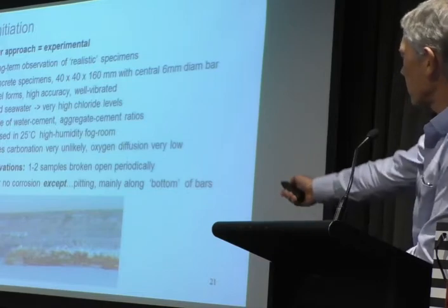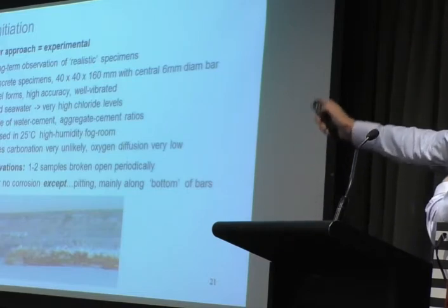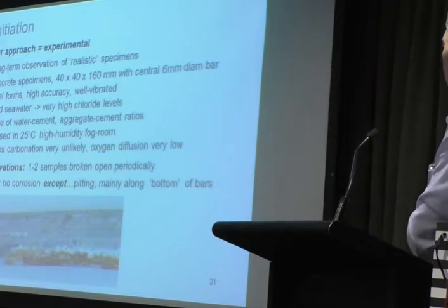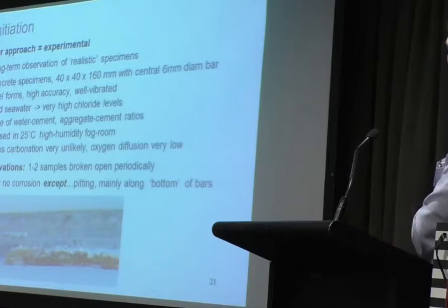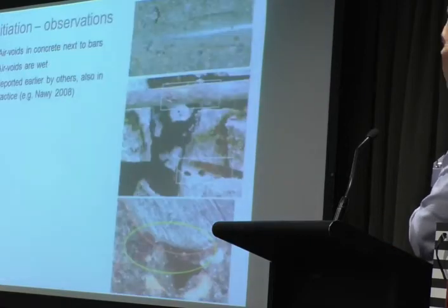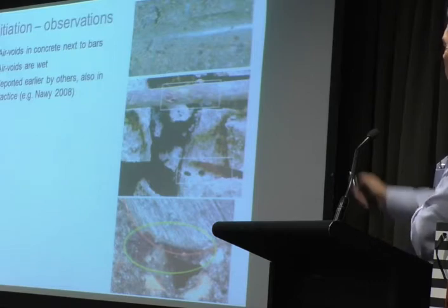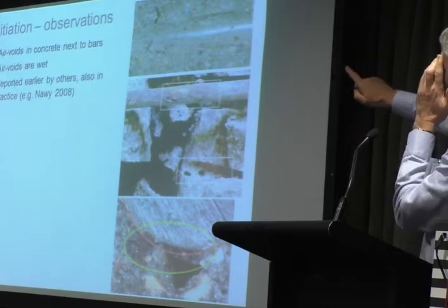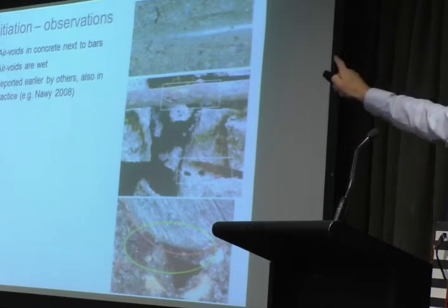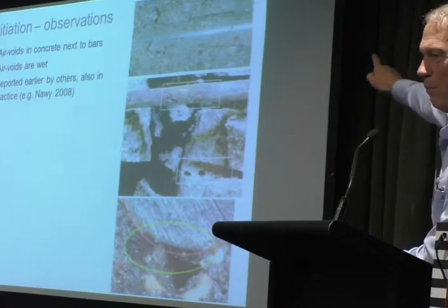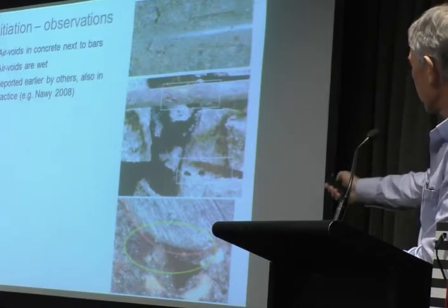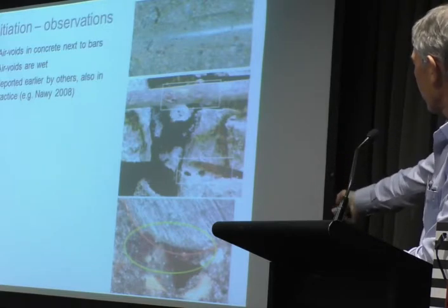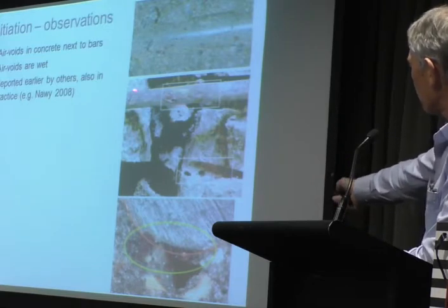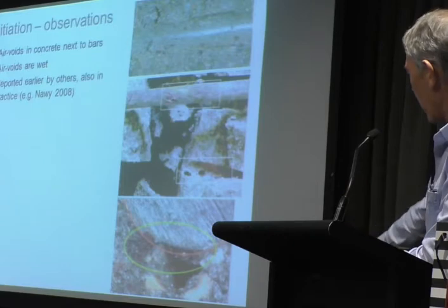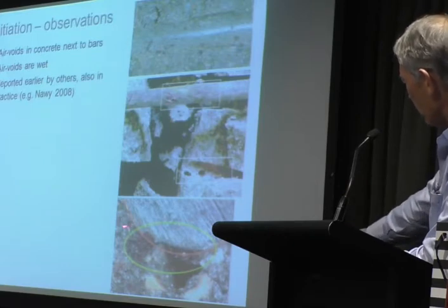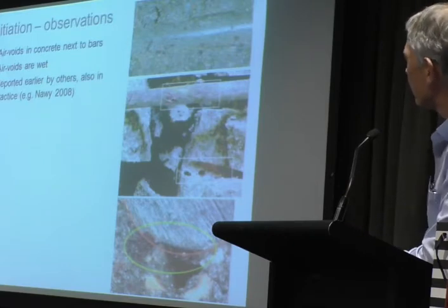You can see it there. This is just one photograph of it, and there's heaps and heaps. I can show you lots more. And they are pitting. And then you've seen a picture a bit like that before. If we then looked at the pitting, it was next to the air voids in the concrete. So the passivation bit wasn't there. And you can see another picture here in the middle showing, this is the separated bit, but here's the air voids, and that's where the corrosion was on the bar. And here's another picture showing the loss along, there's a cross section here.